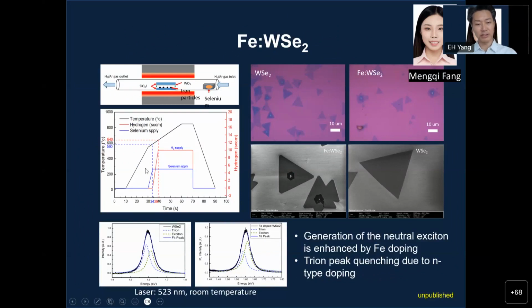conditions to get this growth: the temperature, the supply of selenium and hydrogen, and so forth. On the bottom left, it shows the photoluminescence of undoped and doped tungsten diselenide, showing different generation of neutral exciton, and the neutral exciton is enhanced by iron doping, and trion peak quenching happens due to the N-type doping for this doped material here.